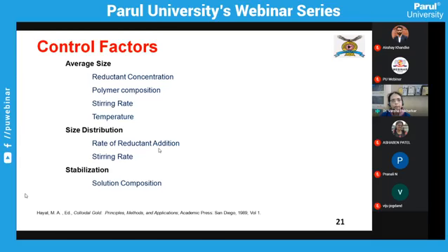So what are the factors that may control the size and the shape? The average size will be dependent upon the reductant concentration, the polymer composition that is used, maybe the stirring rate and the temperature, as well as the time. The size distribution essentially may depend on the rate of reductant addition and the stirring rate. And the stabilization of particles is only attributed to the solution composition.